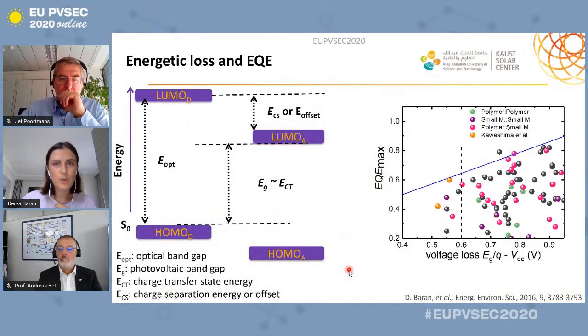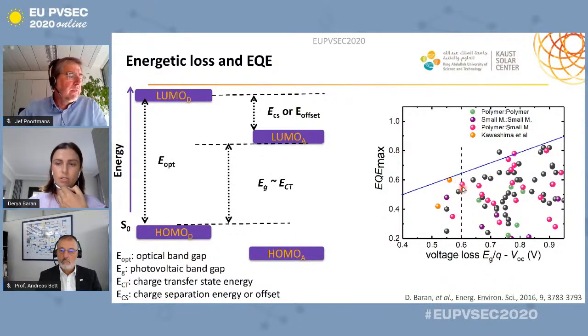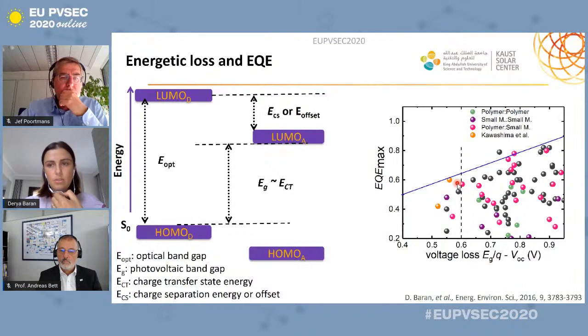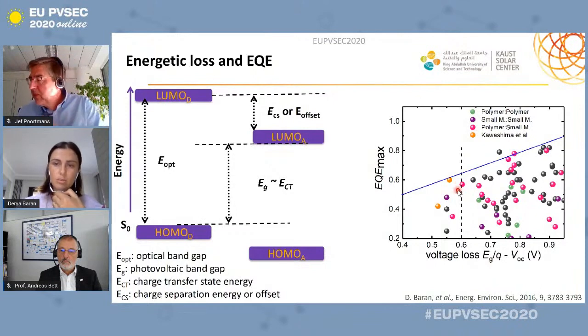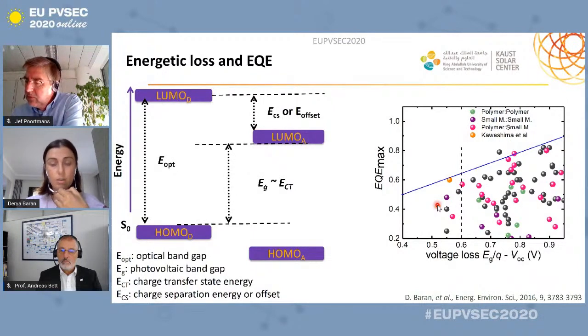But obviously for research purposes, I think most of you would agree that P3HT is not that exciting. And then there are lots of other donors out there, simply because of the huge voltage loss from P3HT to the other acceptors. And this graph was actually quite seminal also in the energetic loss history of OPV, because when you look at it between the donor and acceptors, there was this 0.6 eV I mentioned earlier as the voltage loss set, I would say. Even if you use different donor acceptor combinations, when the voltage loss was lower than 0.6, then you were not able to achieve any decent external quantum efficiencies.